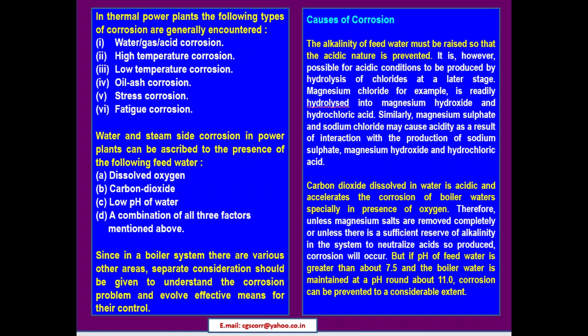Carbon dioxide dissolved in water is acidic and accelerates the corrosion of boiler waters, especially in presence of oxygen. Therefore, unless magnesium salts are removed completely, or unless there is sufficient reserve of alkalinity in the system to neutralize the acid so produced, corrosion will occur. But if the pH of feed water is greater than about 7.5 and the boiler water is maintained at a pH around 11, corrosion can be prevented to a considerable extent.